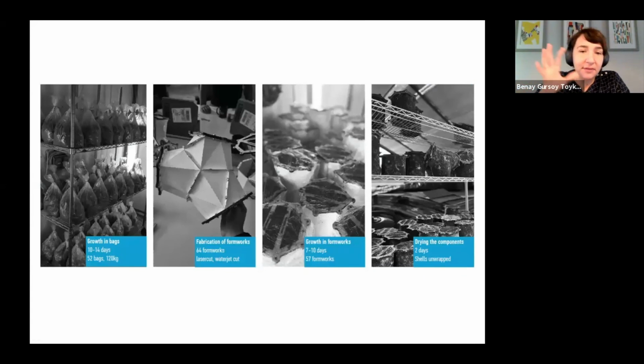The mycelium grew at the Mushroom Research Center in controlled environments for 10 to 14 days in bags. In the meantime, we fabricated the formworks using a laser cutter, and a water jet cutter for the aluminum pieces. Then we filled the formworks by hand, and they grew within the formworks for another 7 to 10 days. And finally, we dried the components. A couple of challenges we had was that because we had a deadline for the competition, the components did not fully dry by then, and it was very humid at that time.